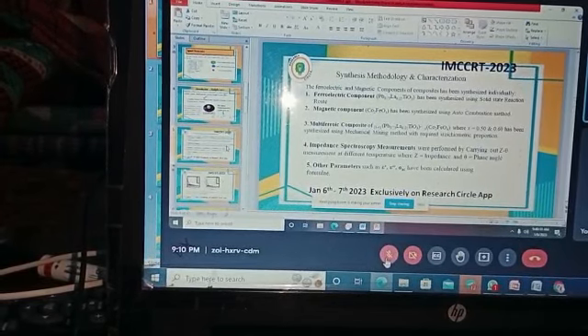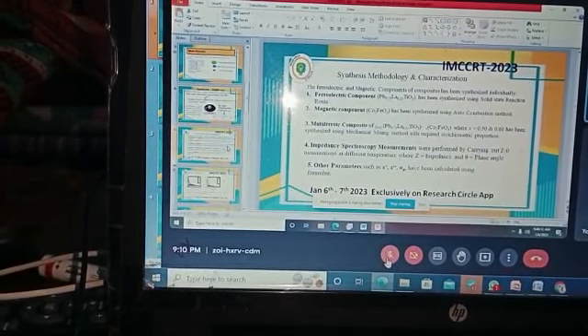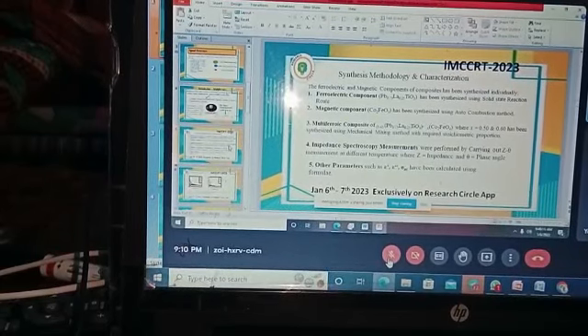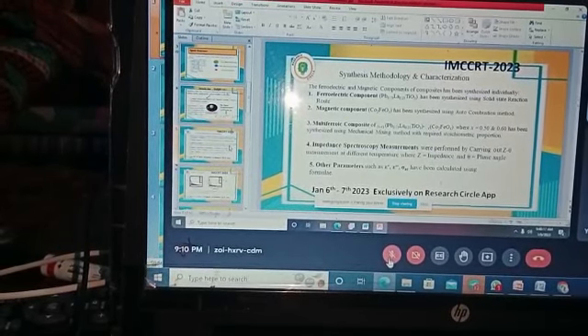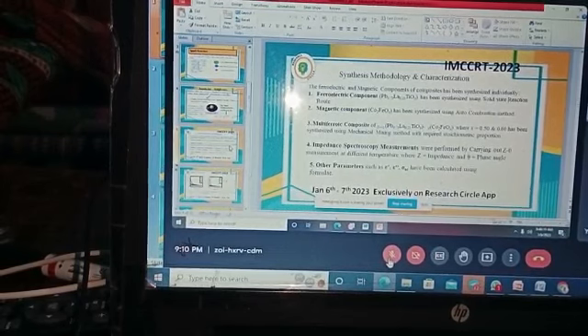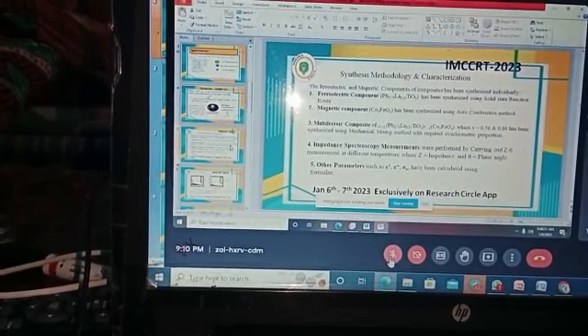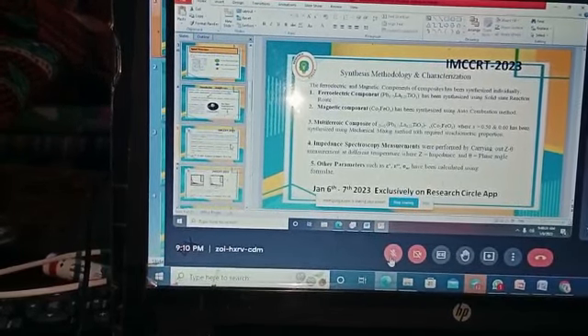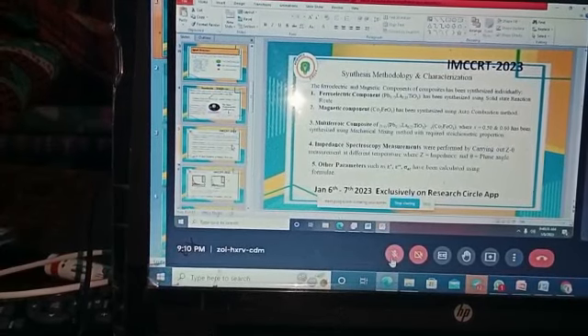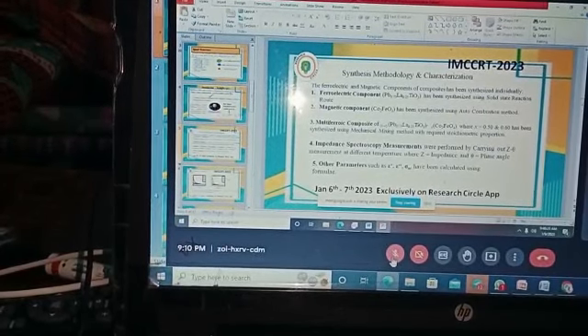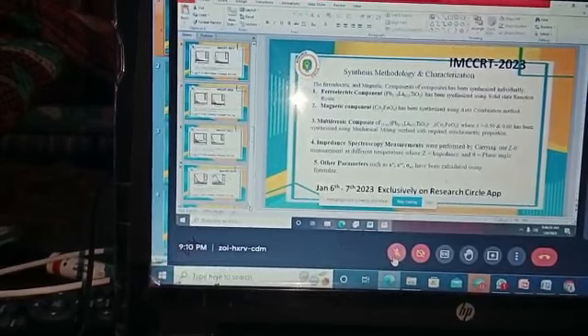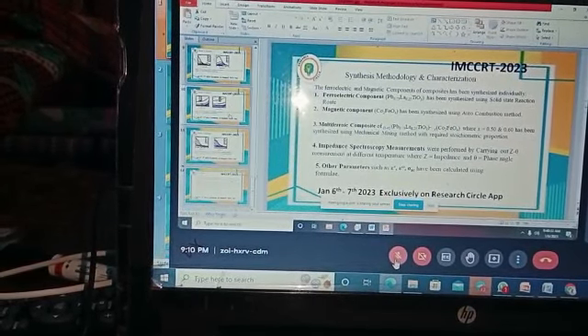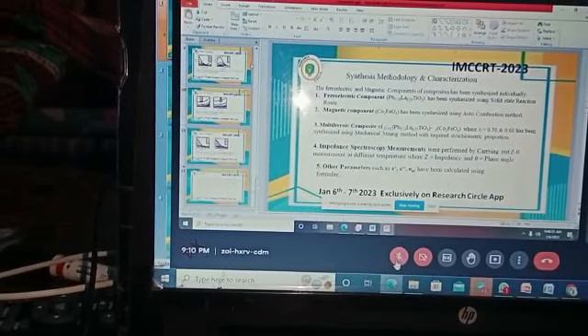The composite of both are synthesized by simple mechanical mixing method. We will perform the analysis at different temperatures, and from that we will find out the real and imaginary parts of dielectric, real and imaginary parts of impedance, AC conductivity, as well as the dielectric loss, that is tan delta.